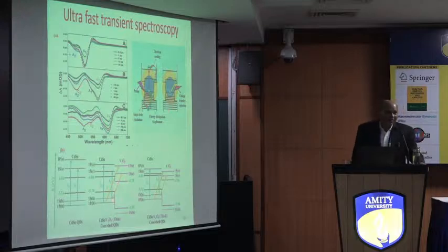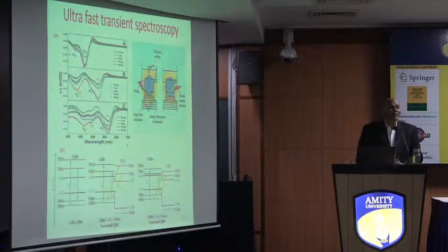Then here what will happen? Here the electron cooling rate decreases. If the electron cooling rate decreases, then such a material can be useful for photovoltaic applications. So this is the conclusion here.